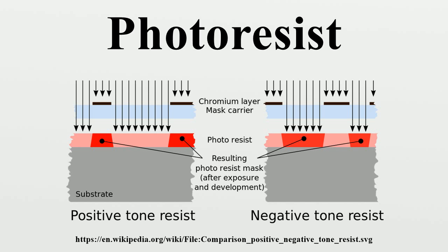The combined benzene chromophore and DNQ Novolac absorption mechanisms lead to stronger absorption by DNQ Novolac photoresists in the DUV, requiring a much larger amount of light for sufficient exposure. The strong DUV absorption results in diminished photoresist sensitivity. Photoresists used in production for DUV and shorter wavelengths require the use of chemical amplification to increase the sensitivity to the exposure energy, in order to combat the larger absorption at shorter wavelengths. Chemical amplification is also often used in electron beam exposures to increase sensitivity to the exposure dose.